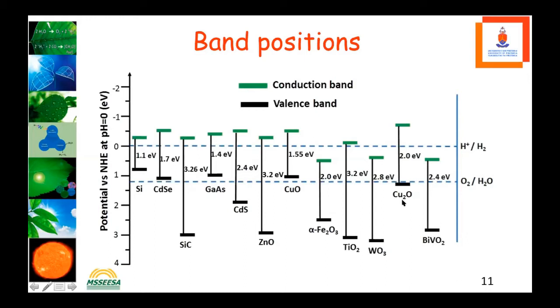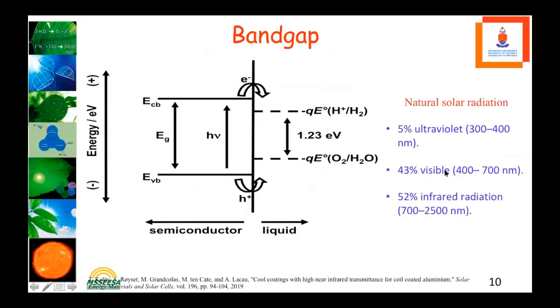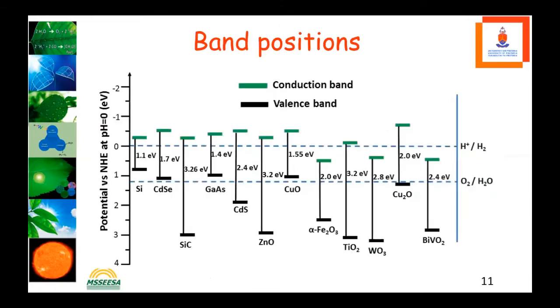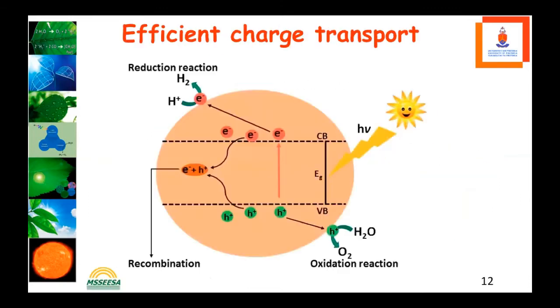But then we have found that hematite is the better electrode for us. You can see 2.0 or anything that lies around there, according to this, between 400 and 700, you'll harness more than 40% of the solar radiation, which is very important to this kind of studies.